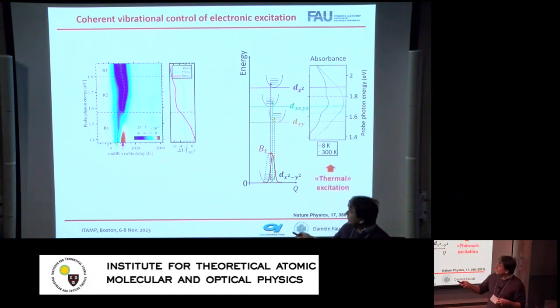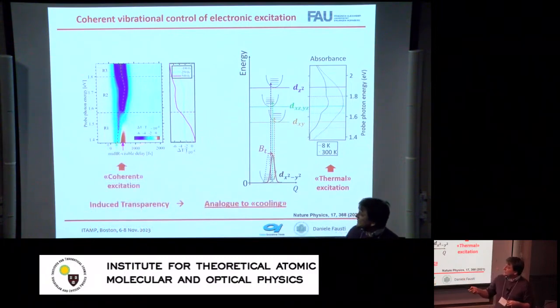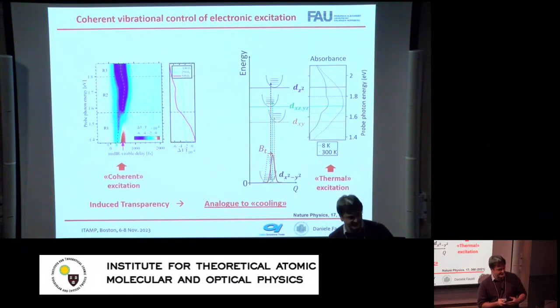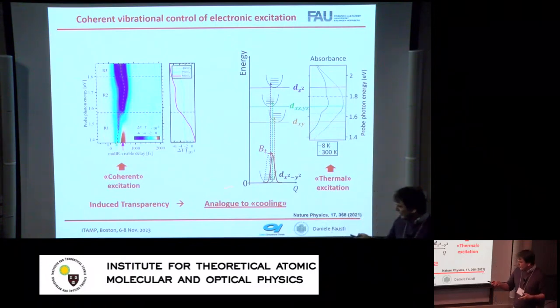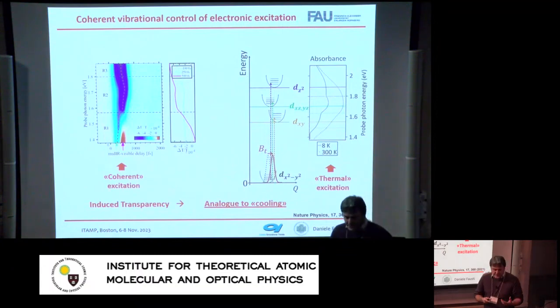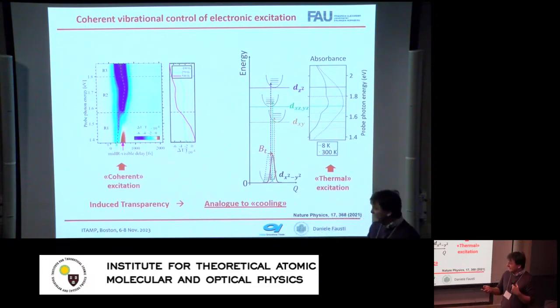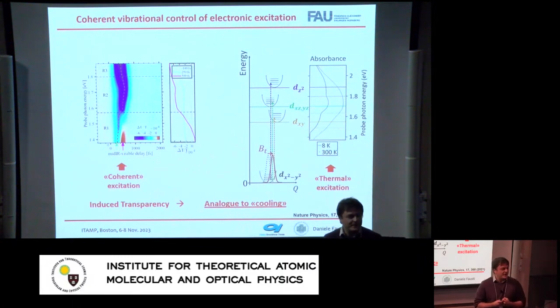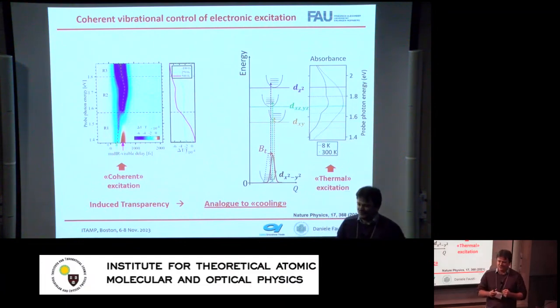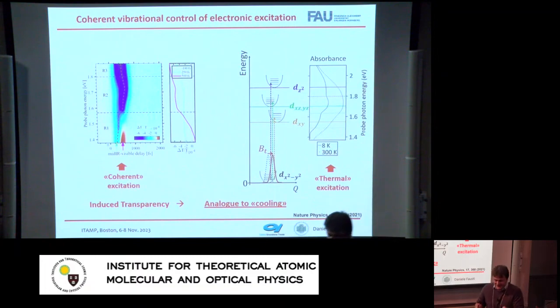On the other hand, out of equilibrium, we revealed a region where I increase the transparency of the system. And increasing the transparency allows me, in a formally non-correct analog, but essentially it tells me that by putting energy into the system, I can produce a situation in the material which is analog to cooling the fluctuations of the material. And the fact that I can go to a transparency which is larger than the transparency I have at zero temperature, it means that I can cool. If I want to say something fancy, I would say I cool it beyond the vacuum fluctuations of the system, but to say it honestly, we do something else. Okay, we drive the ions and we do something else.